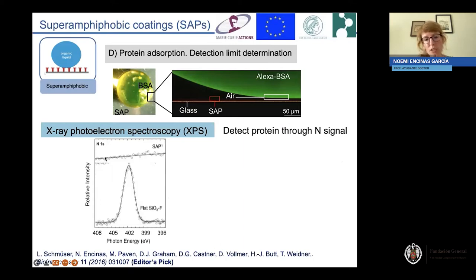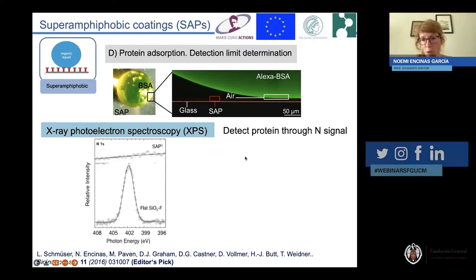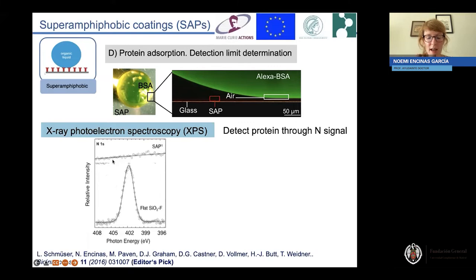So here we basically went to better tools, let's say really sensitive tools. So we used X-ray photoelectron spectroscopy and the signal of nitrogen as a probe to detect proteins. We used this signal because the rest of the signals that could lead us to think that we had proteins were also common to the surface, so for example, silicon, oxygen, etc.